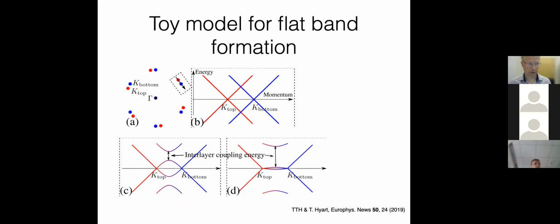The toy model for this flat band formation is here. You consider these twisted reciprocal lattices, and then look at this vector connecting the two reciprocal lattices. As a function of this vector, you can find, in an uncoupled case, two Dirac points, the red and blue one, which correspond to the two layers.